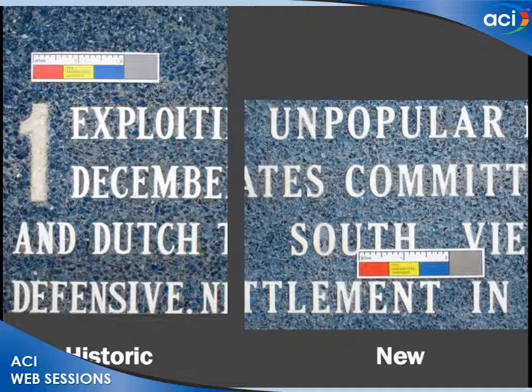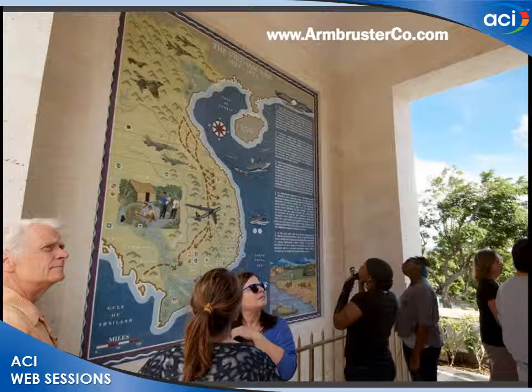Turned out quite well. We were very pleased. You can see that's actually one blue aggregate, but it looks dark blue, light blue, a little gray, all because of the orientation of the glass and the thickness of the glass in the individual particles. Here it is with the marble cladding surrounding it and covering the structure and the visitors there looking at it. Everyone felt that it was very effective.